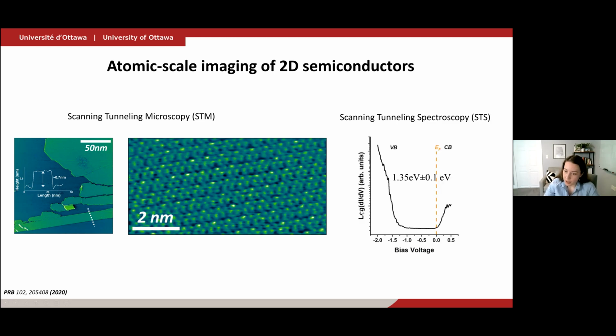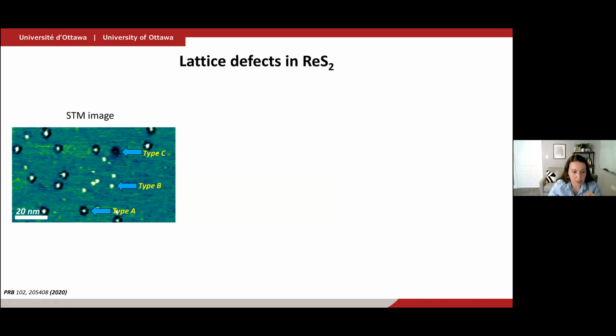Through spectroscopy, we measure the derivative of the tunneling current with respect to the voltage as we apply a bias between the tip and the sample. Such a measurement gives us a quantity that is proportional to the density of states. So if you're used to semiconductors, in such a spectrum that we take on a 2D semiconductor, we find the valence band, the semiconducting gap, and then the conduction band. In this case, the semiconducting gap was found to be around 1.3 eV. And we find that the Fermi level in this particular semiconductor was very close to the conduction band. As we saw that, it was then not surprising that as we scan the surface, we find very often these point-like defects everywhere.